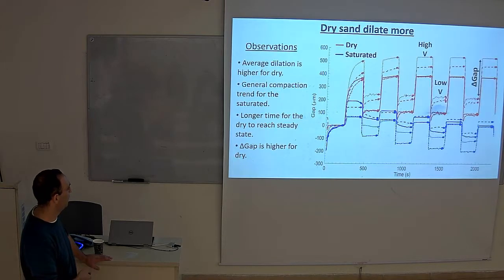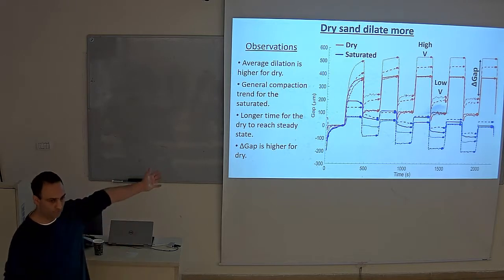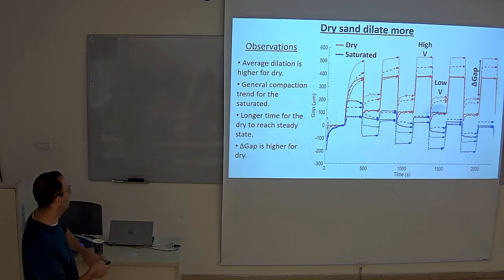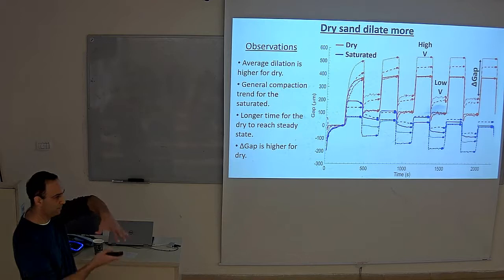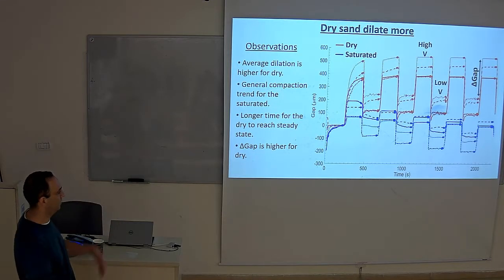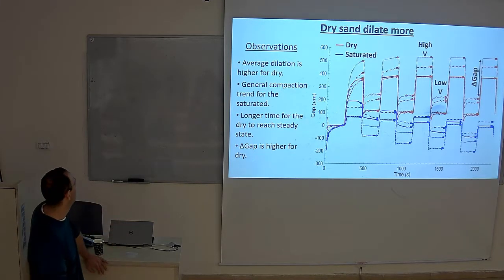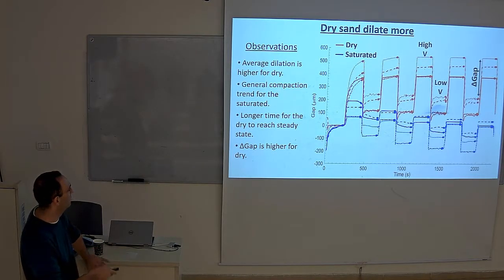And let's move to the dilation measurements. So indeed, we see the same pattern of the velocity in the results of the dilation compaction, the gap in microns here. So increasing the number here is dilation, more opening of the system, increasing volume. Down to lower numbers is decreasing the volume, compaction. And the observation we have, so first that's the time of the experiment, of course, dry experiments in red, water saturated in blue. And dilation is higher for dry.